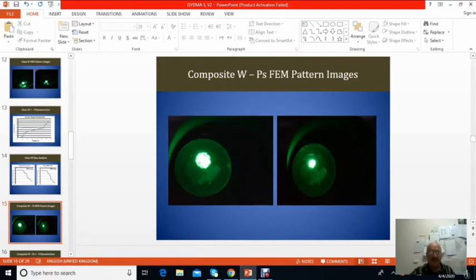tungsten polystyrene field emission microscope pattern images, this is the same image, just enlarged here, just to show that there is a structure inside here. While in the normal epoxy resin, we did not see any such structure. It was just a bright spot without any structure.